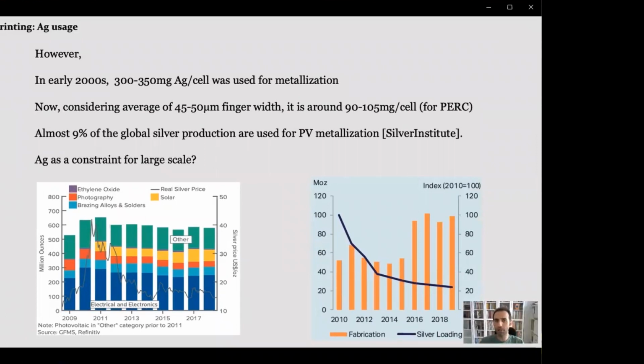This is proportional to the width of the fingers because the wider the finger, the more the silver used. For example, in early 2000, the contact width was around 200 micrometer, and that corresponded to almost 350 milligram of silver per cell. As of today, with improvements in the screen printing and optimization of the pastes, the average width is 45 to 50 micron, which is around 100 milligram per cell.